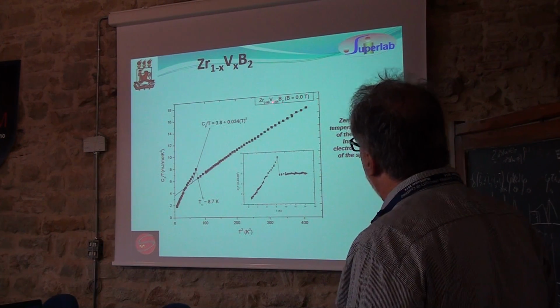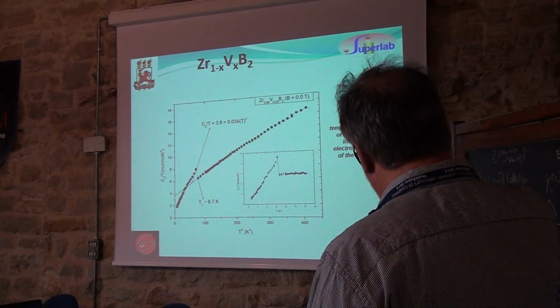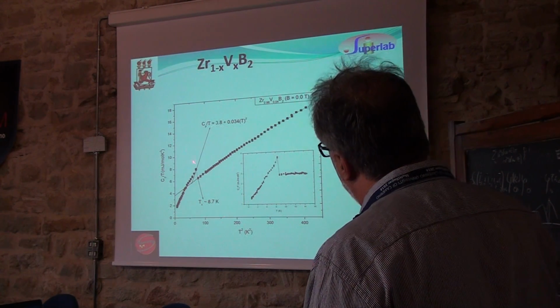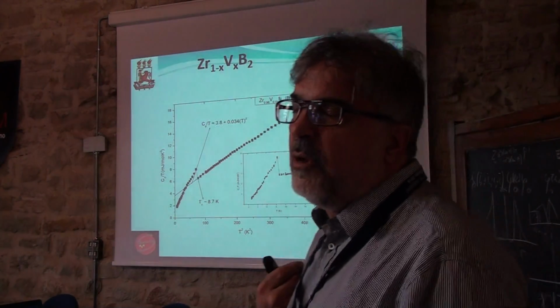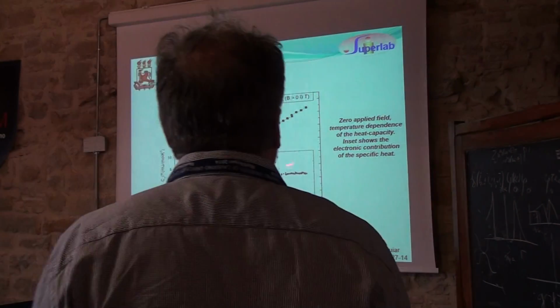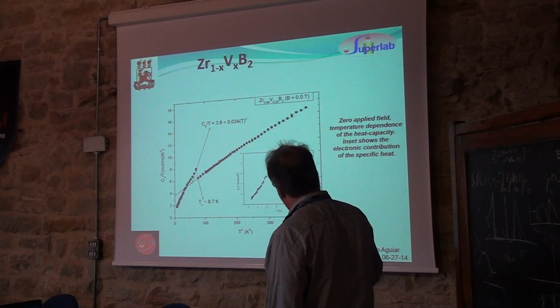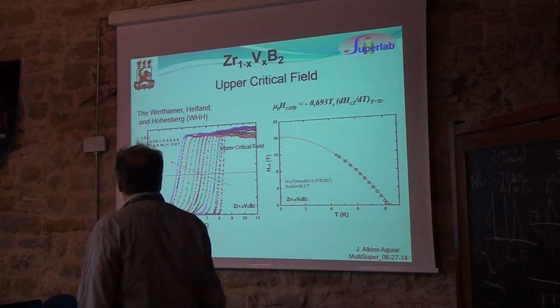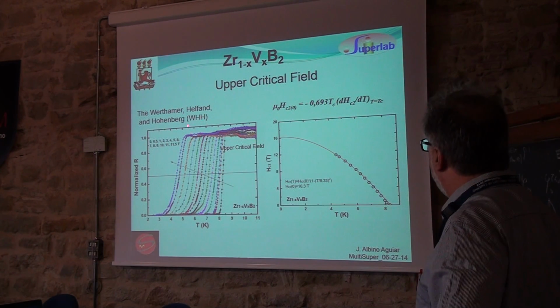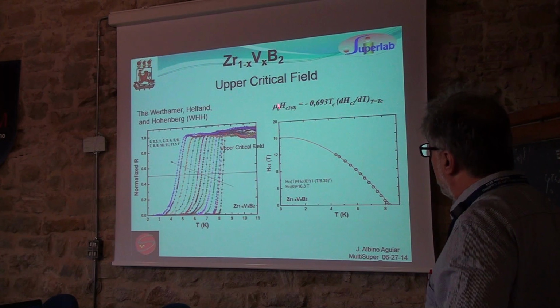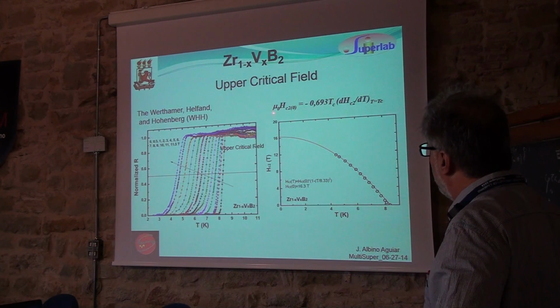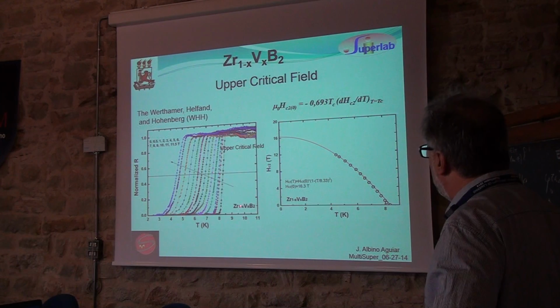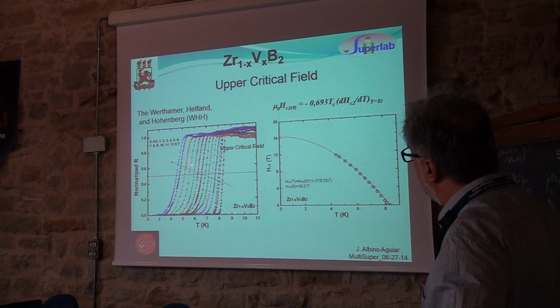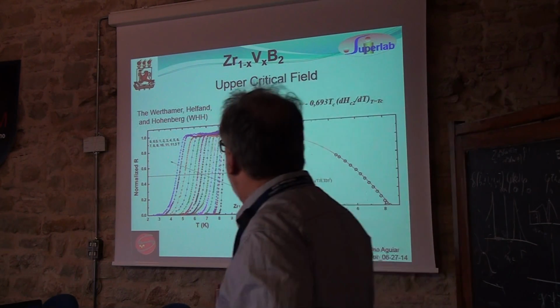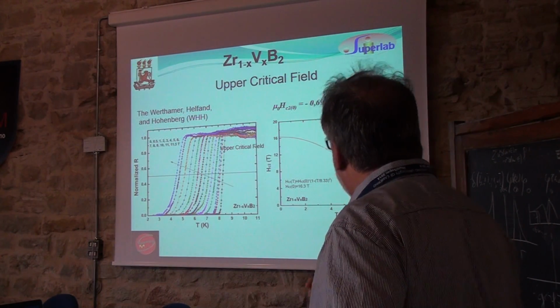Again, at zero field for the same sample, we have the heat capacity data. And you see there is a fitting, you see that there is a jump at the transition temperature. So we have no doubt that this is a bulk superconductor. If you subtract the phonon contribution, you get this. Now let's go to see what we get for the upper critical field. So these are the measurements that I mentioned that they are very tough. Here you have the resistivity transition as a function of field. And this is for the 0.96% zirconium, field increasing in this direction. And if you use the Werthamer-Helfand-Hohenberg model, you can fit like this.